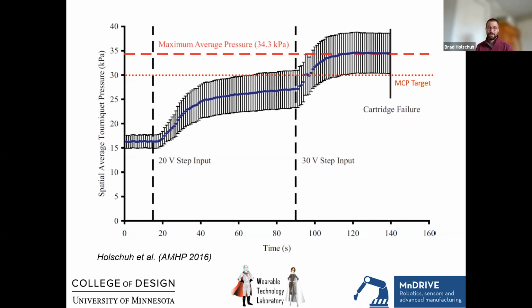We exceeded it. Starting at a pressure of about 15 or 16 kilopascals, applying a few step inputs in voltage, you can see the pressure reliably increase. As you increase the voltage, so too does the pressure, because the stiffness of the materials is increasing. And we landed at 34.3 kilopascals. We beat the target by more than 10%. When I got that data, that was when I started celebrating, saying, hooray, they're going to let me graduate. I solved the problem.